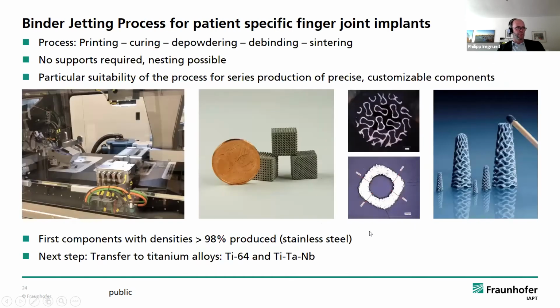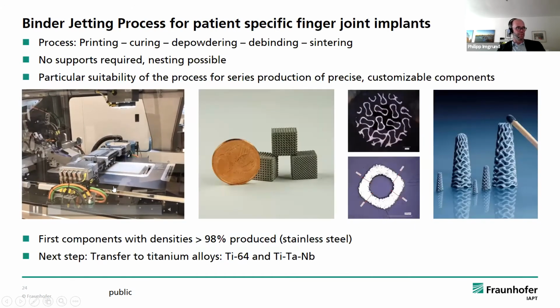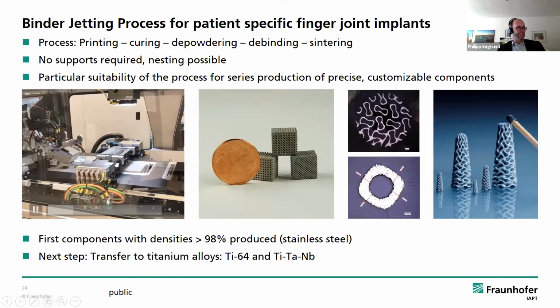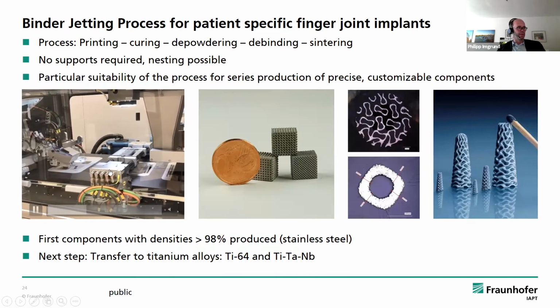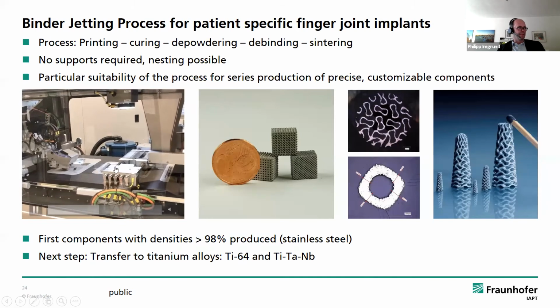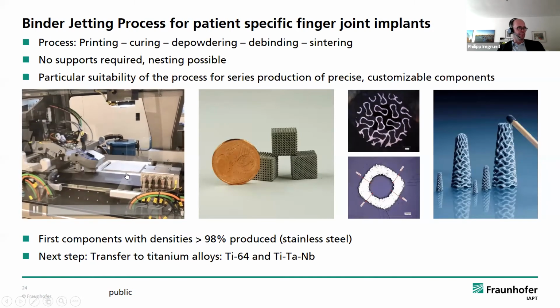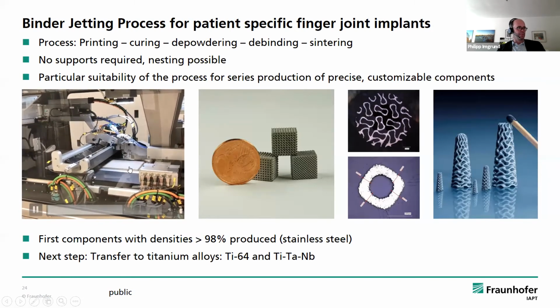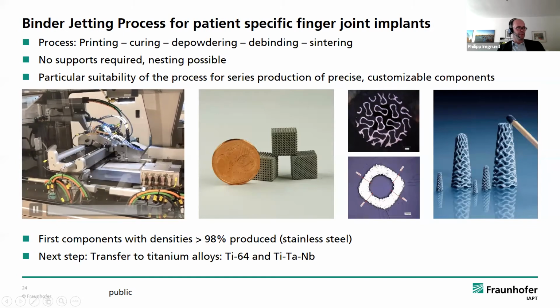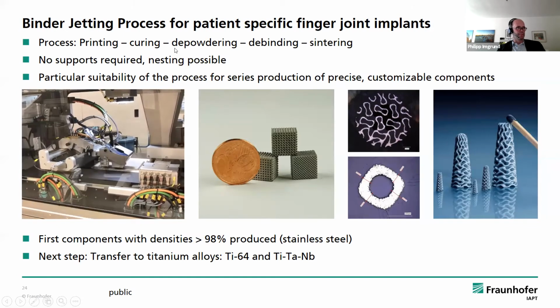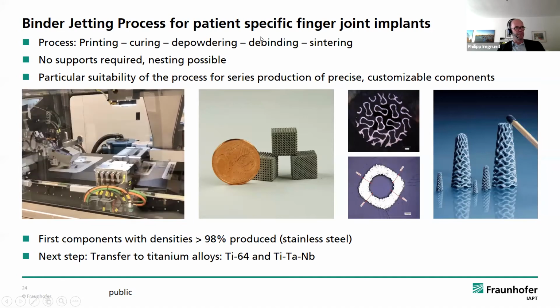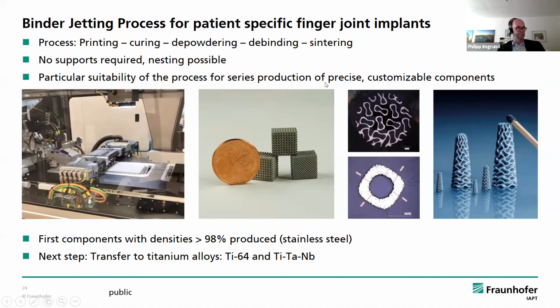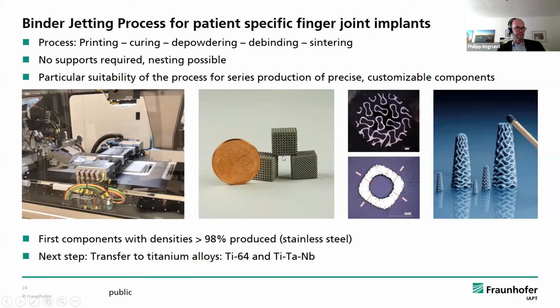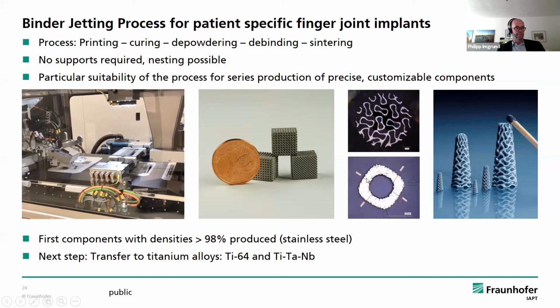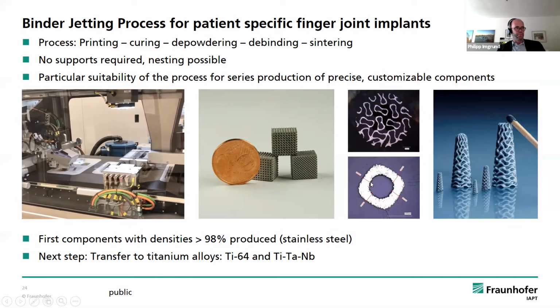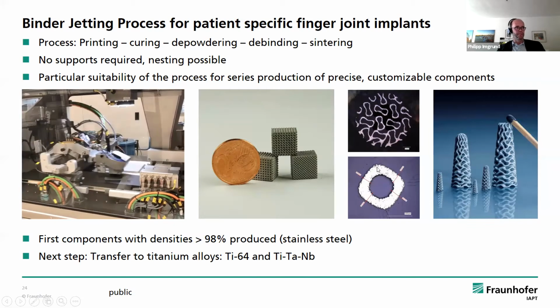And so I want to also show you. So here you have a sneak peek at the process. You see the powder bed here to the left. And after the powder is dispensed, you have the inkjet printer that prints the ink into the parts. And then after this printing process, you come to curing, depowdering, debinding, and sintering. So it's a multi-stage process. Main advantage is you can really go to very tiny and precise structures. So they are in the range of 300 microns, 200 microns, the wall thicknesses here.